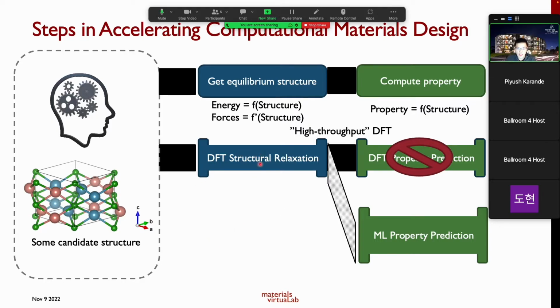We still have a bottleneck, right? One of the main weaknesses of graph neural networks is that you need the input graph, and you usually obtain the input graph from the DFT relaxed structure. Now, if I have to do a DFT relaxation, that kind of defeats the purpose, right? So now my pipeline is no longer bottlenecked by property prediction, but by my DFT structure relaxation.